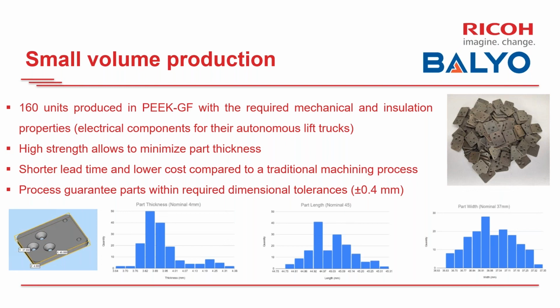So we produced 160 units of this connector. You can see a picture of the full set of parts here. These were produced in just a couple of weeks, providing a lead time that is 3 times shorter than a machining option for a reinforced material. There was also a cost saving of around 30% compared again to a machined solution. And in the end, the standard dimensional tolerances of the part, even just after the first iteration, were within the tolerances required by the application.